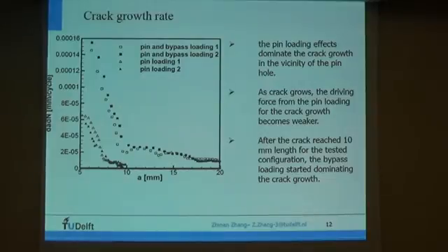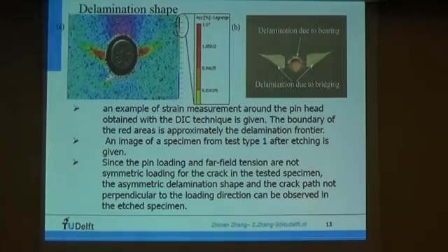It can be easily found that the pin loading effect dominates the crack growth in the vicinity of the pinhole. We can see here, as the crack grows, the driving force from the pin loading for the crack growth becomes weaker. After the crack reached 10 mm length for the test type 2, the bypass loading started dominating the crack growth. That's the result for crack growth rates.